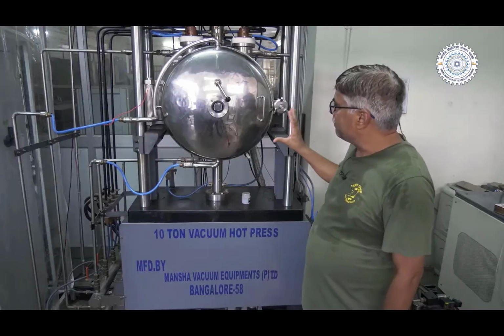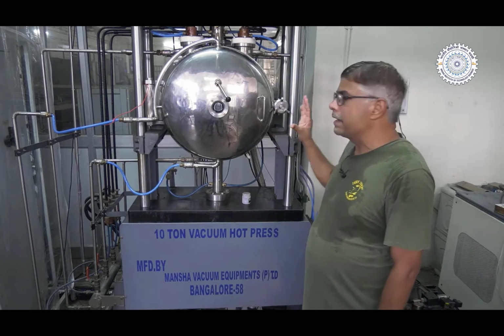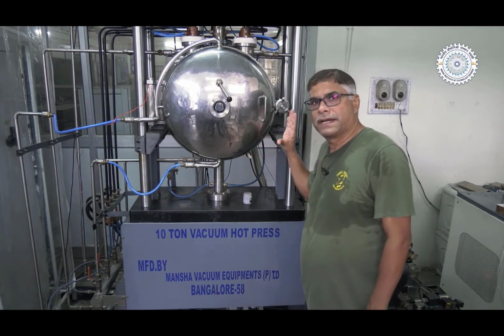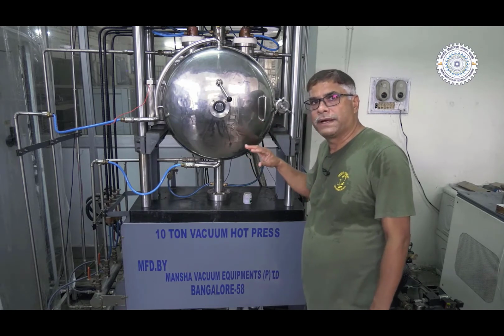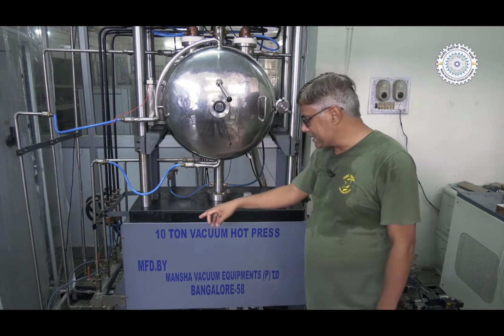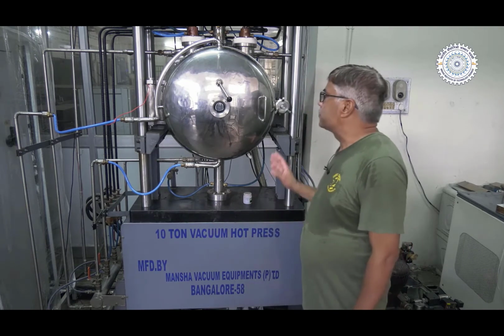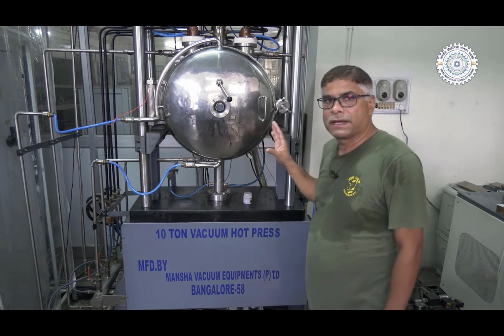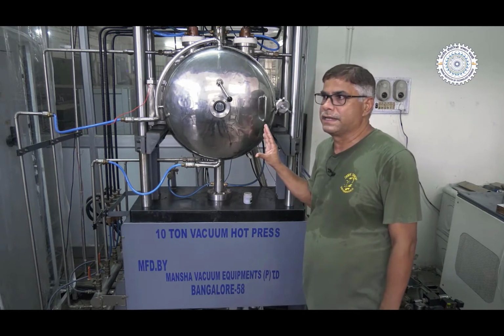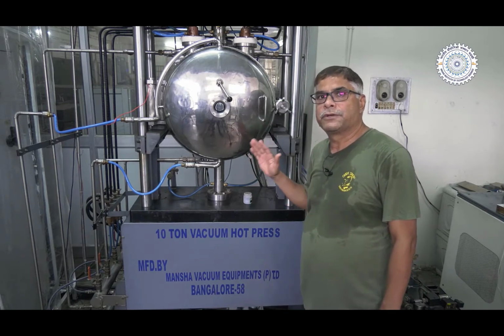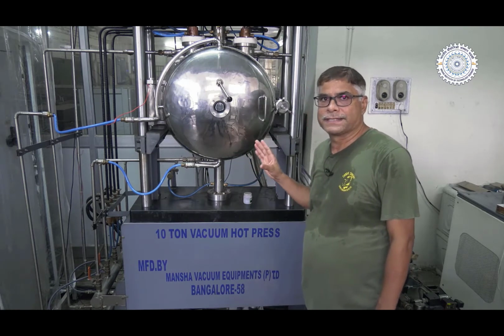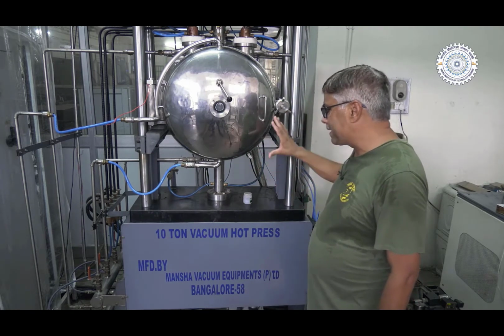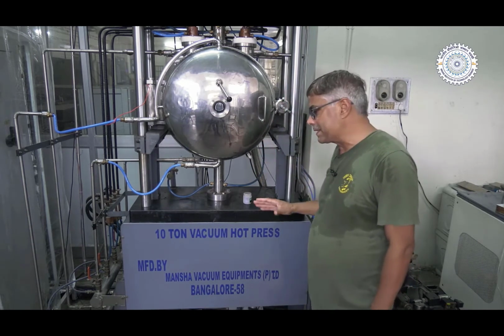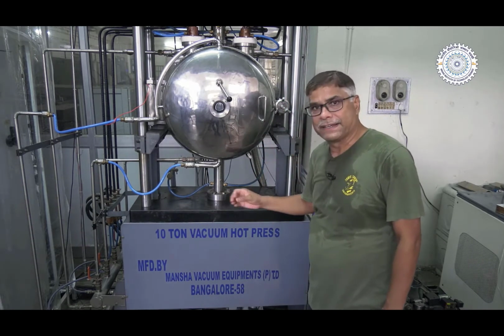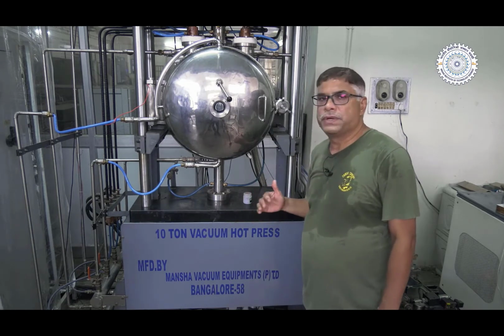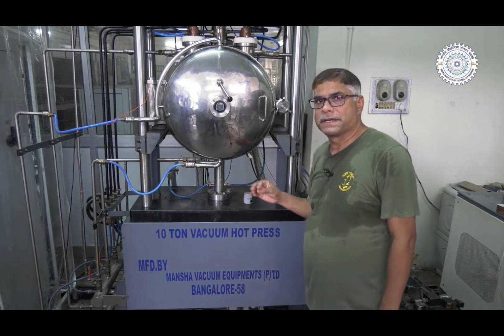In this chamber, we create the desired high temperature and the desired vacuum, and the components to be joined are kept under pressure. Since this is a 10-ton vacuum hot press, the temperature of the vacuum chamber can be increased up to 1200 degrees centigrade, the vacuum as low as 10 to the power minus 5 torr can be realized, and the load can go up to 10 tons. We have worked up to 20 MPa, 40 MPa kind of pressure to have the diffusion bonds.